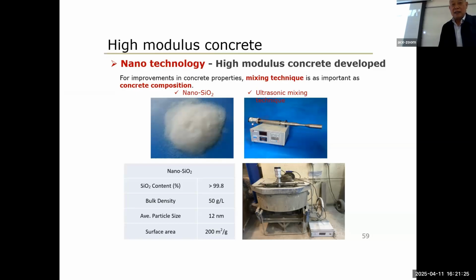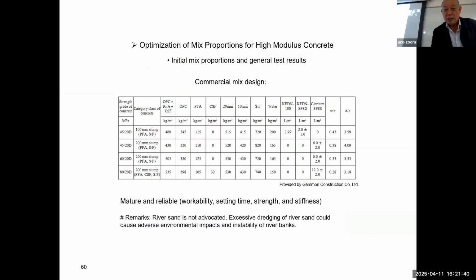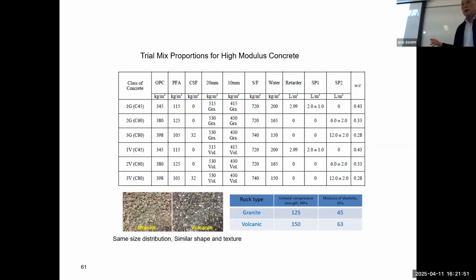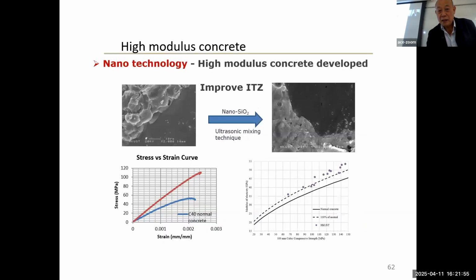This is one I did at HKUST. What we did, we added nano silica into the concrete. We tried to produce concrete with a high modulus. So we started from this commercial mix design. This is from Gammon Construction Co. Ltd. At that time we were the partner. And then we modified that formula into this high modulus concrete formula.